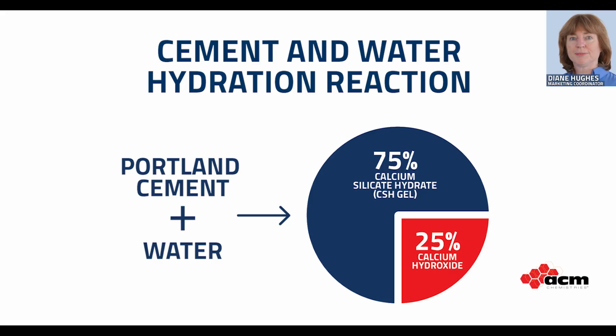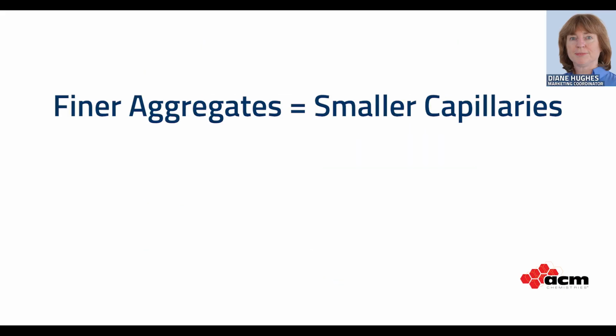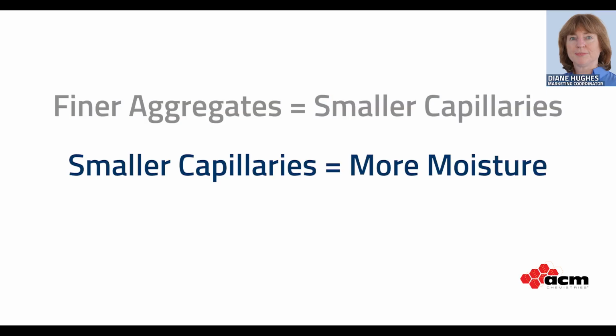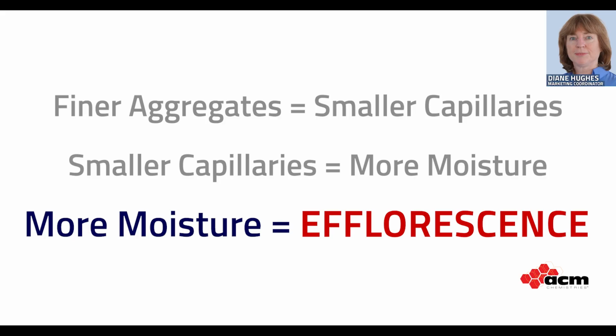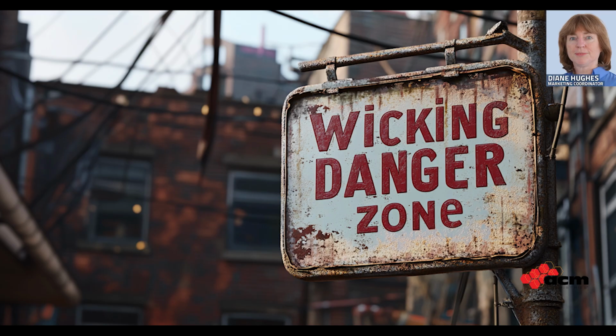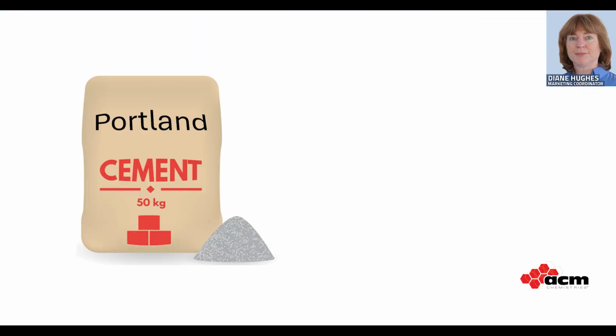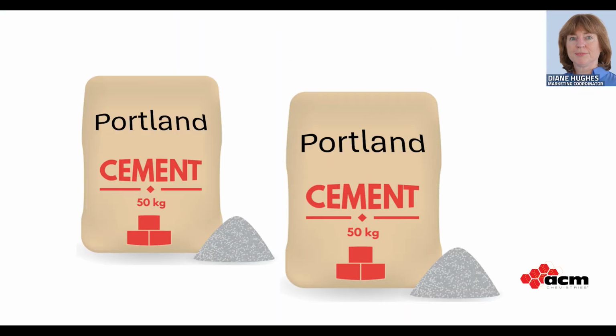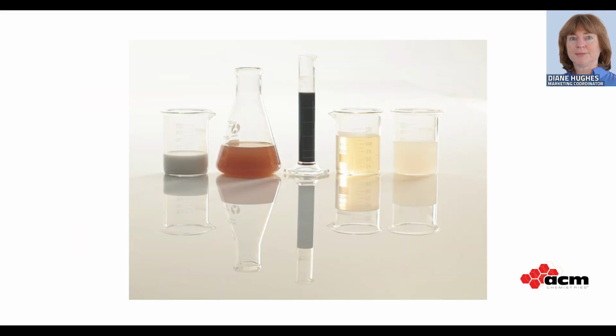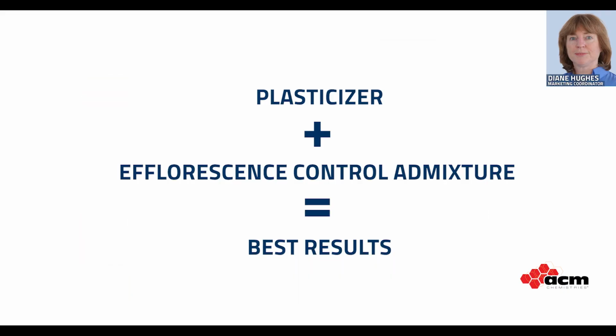The second reason is that cementitious particles are very fine, and as we know, adding more fines typically makes voids and capillaries smaller, with more efficient wicking power and more potential for efflorescence. Once we're in the wicking danger zone, the best strategy is often to just double down and physically or chemically block the pores as much as possible, either with even more cementitious materials or with an efflorescence-reducing admixture. Admixtures. Most producers find that using a plasticizer in combination with an efflorescence control admixture delivers best results.